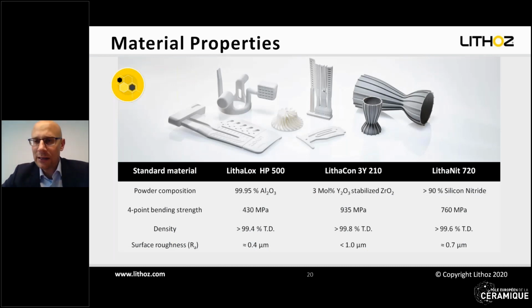Let me go now into some of the details to show you what we can achieve with our standard products. For example, one of our first products was LithaLox HP 500, which is an alumina. It has a 4-point bending strength of more than 400 megapascals and a density well above 99%. And very special, I think, is also the surface roughness. It's well below 1 micron. The same is true for zirconia. So we have here 3-mole yttria-stabilized zirconia. Also a 4-point bending strength of nearly 1000 megapascals, and a theoretical density of nearly 100% again.